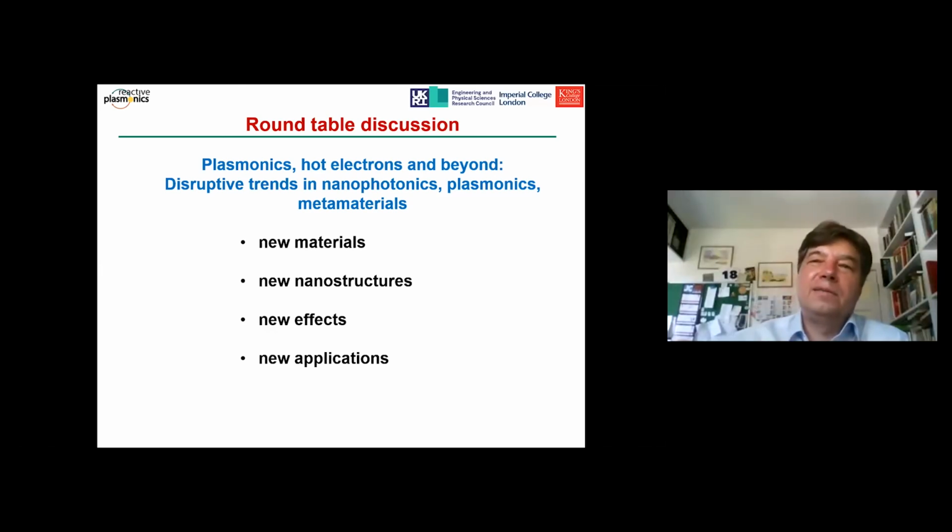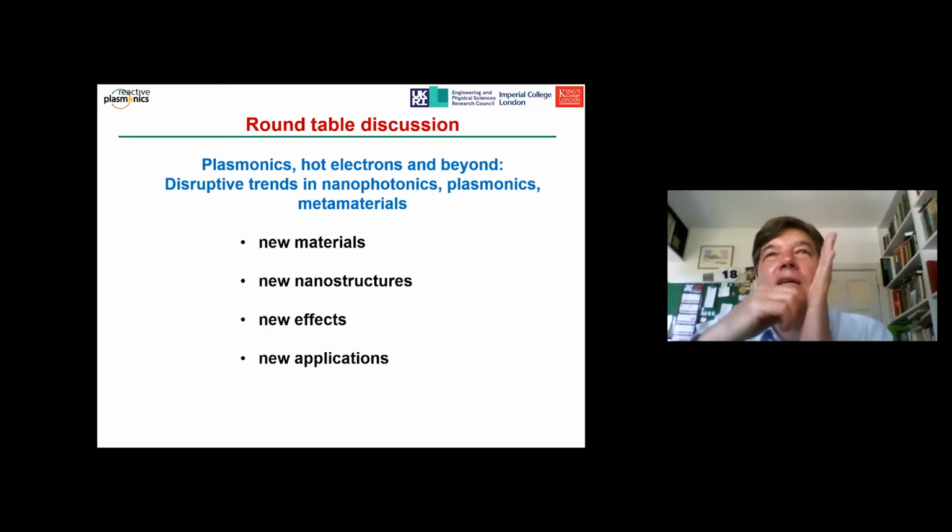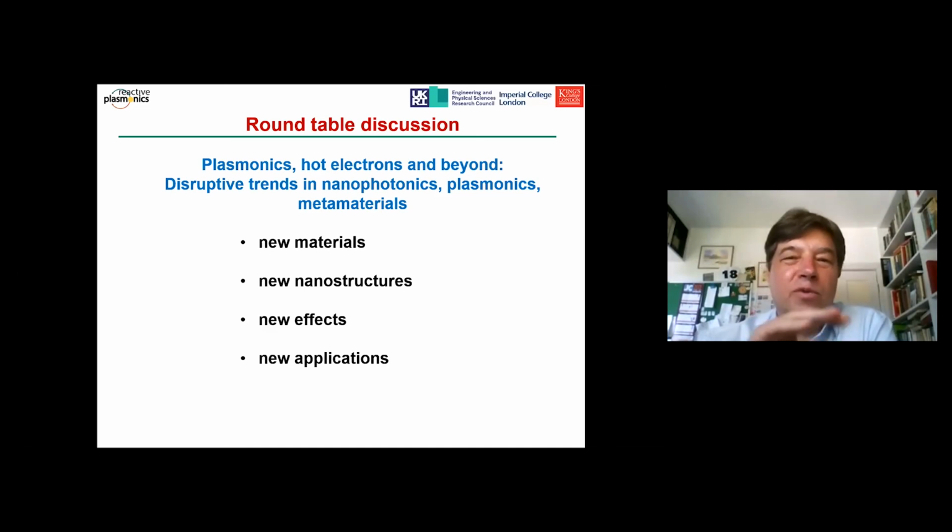Yeah, exactly. So I remember a couple of years ago when Jeremy Baumberg was studying these small gaps between nanoparticle and thin films. His example was that in this gap, actually, what you see is not an interface, but a kind of soup of atoms, gold atoms, because at this scale you have to already take into account motion of atoms, and so there is no real interface, or at least no interface in the sense of a rigid interface.